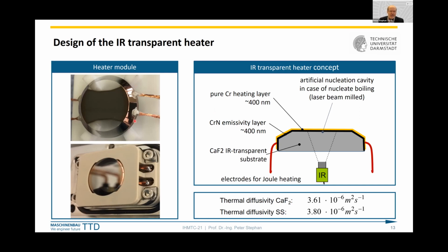These are the electrodes. We have 4 electrodes, 2 on each side of the heater, contacted on the pure chromium layer, with the heating system on top of this infrared transparent glass. By applying voltage through these electrodes, we have Joule heating, giving us heating and a temperature profile measurement directly at the heater surface.